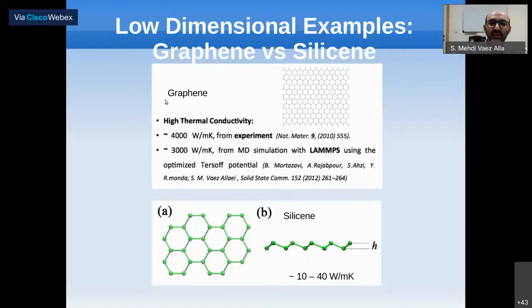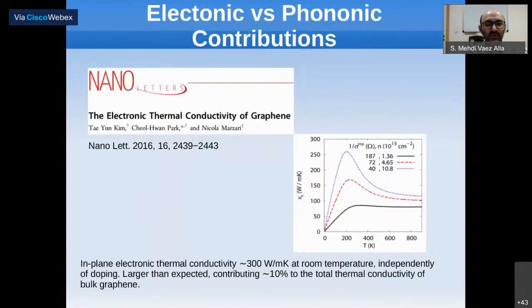For instance, consider the graphene case. We have very high thermal conductivity, somewhat near to diamond, 4,000 watt per meter Kelvin. And with almost the same structure, we have silicene with very, very lower values. It means that we could use this kind of structure in different systems for introducing a very good, possibly thermoelectric device, and also possibly a high thermal conductor to remove an unpleasant magnitude of heat from the system.